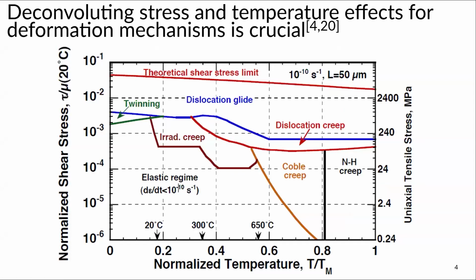This is a deformation map of 316 stainless steel. And you can see based on your normalized temperature, so that's your operating temperature divided by your melting temperature, it's normalized. And then you have your stress, so your applied stress on the y-axis. So it's a function of temperature and applied stress. And so in each of these regions, there's different dominating mechanisms. However, in irradiation creep, this regime has about 6 or 7 proposed mechanisms. So we don't fully understand what actually happens. And so that's my focus here.